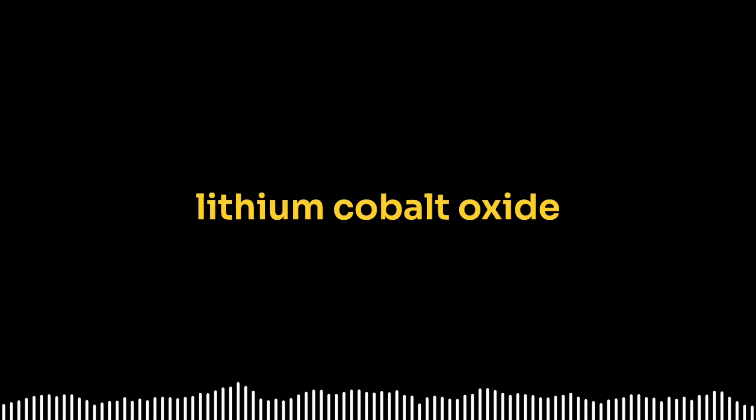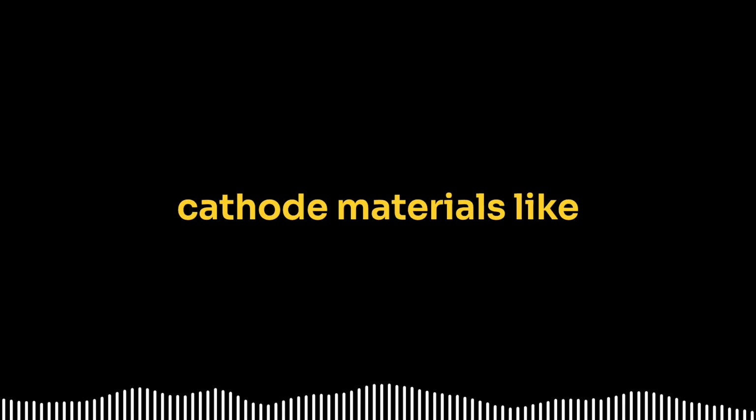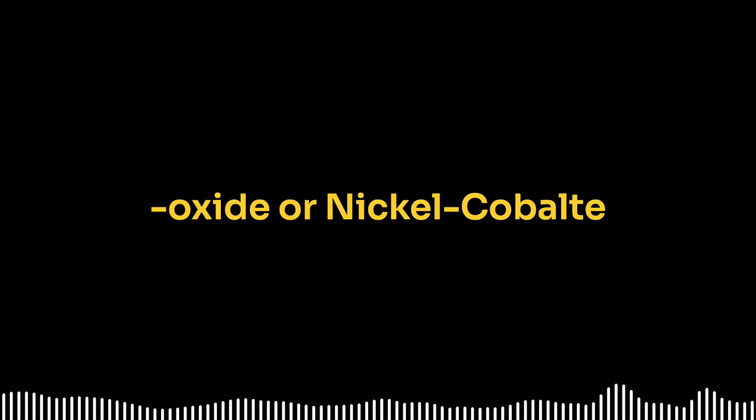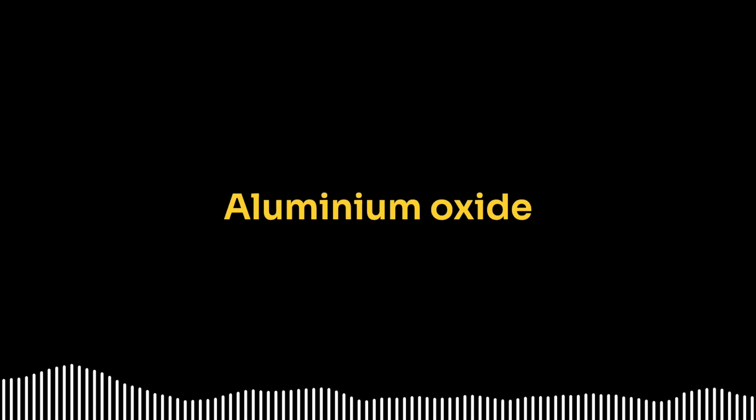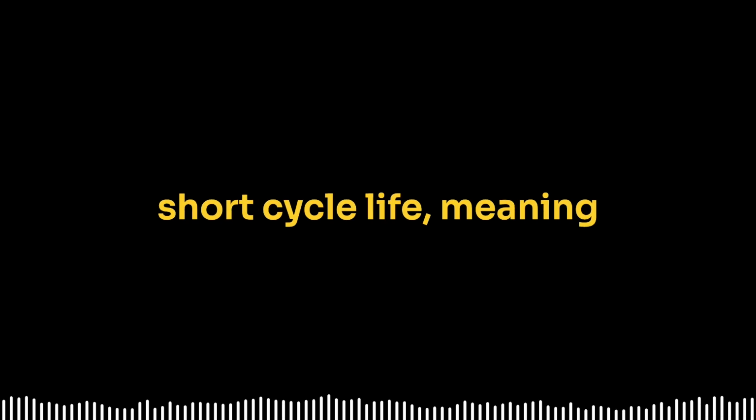Because of this fundamental instability, lithium cobalt oxide cannot be safely used in electric vehicles, where batteries regularly cycle through high voltages and store large amounts of energy. Instead, safer, more stable cathode materials like nickel manganese cobalt oxide or nickel cobalt aluminum oxide have replaced LCO in EV applications. Beyond safety concerns, LCO also has a relatively short cycle life, meaning it wears out faster than other